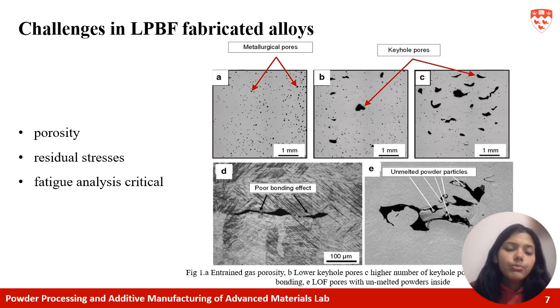So we know that the problem lies in the inherent defects in the process itself. These defects act as stress concentrators and drastically reduce fatigue life. In addition, the unique microstructure resulting from the LPBF process creates non-uniform mechanical properties, and understanding this interplay between the defects and fatigue is essential for enhancing the material's performance and extending its application scope. So here you can see in the image that I took from the paper, there are traces of gas porosity. There are lower keyhole pores and a higher number of keyhole pores in these pictures.